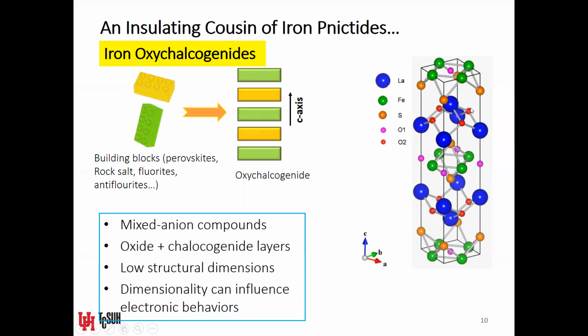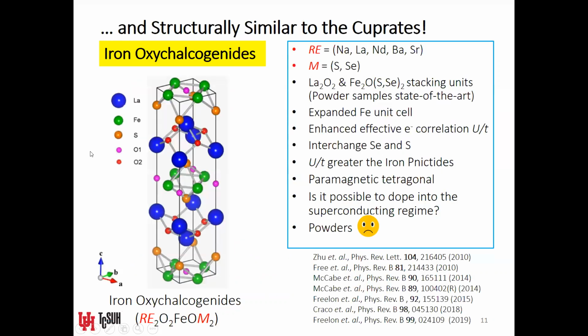So it's almost like a charged reservoir and a conducting layer built in an alternating fashion along the C-axis. Okay, at the top of this figure, I'm circling with my mouse the actual iron chalcogen layer. All right, so I have a better slide of that here. And there are some important things to point out. So there's a similarity between these materials and the cuprate, as I just referenced, going back to the charged reservoir conducting layer. There is an iron chalcogen layer that's analogous to the iron pnictide layer.